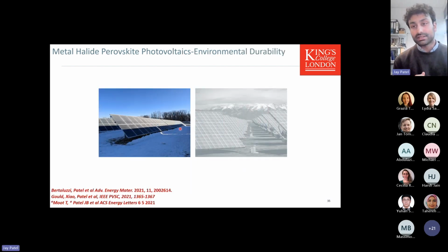The second thing that I looked at was the partial shading effect. What happens in partial shading is, as you can see in the modules over here, part of the module is illuminated and the other part is dark. The part that's illuminated still generates current. The solar cells are all connected in such a way that you need to allow this current to pass through. To do that, the dark panels go into a negative voltage to allow this current to go through. In silicon, that's perfectly fine. It has no problems changing the voltage and passing the current through. We were curious to know what happens with perovskites.